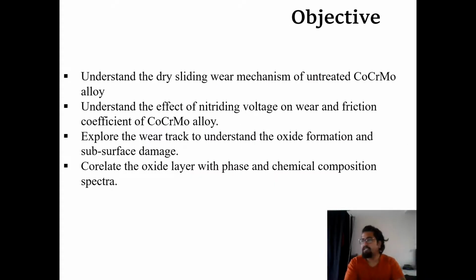My objective in this talk is to understand the dry sliding wear mechanism of the untreated CoCrMo alloy, which is still not known, and to understand the effect of nitriding voltage, because we have changed the nitriding voltage from -700 to -1100 volt, and to see how the microstructure as well as the layer composition changes.